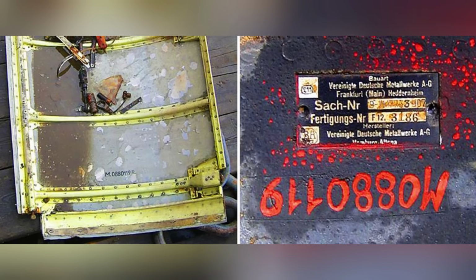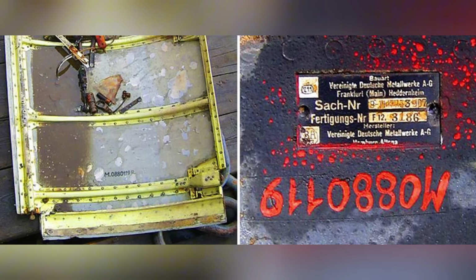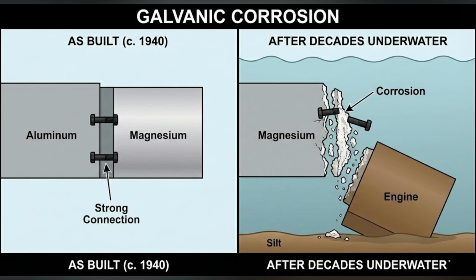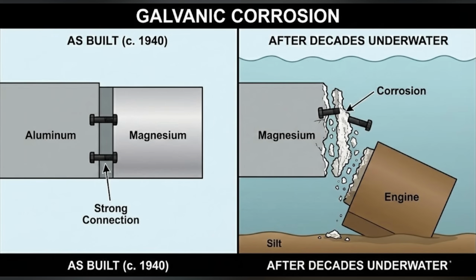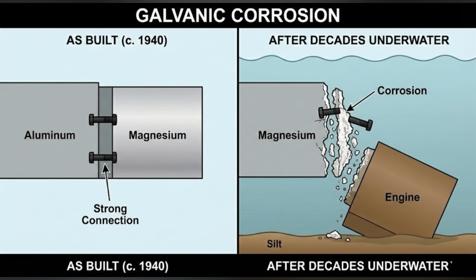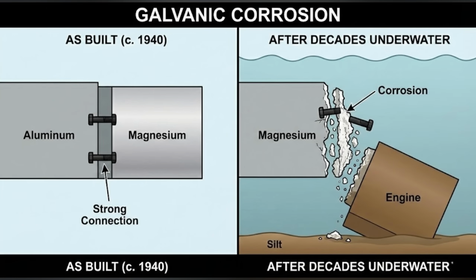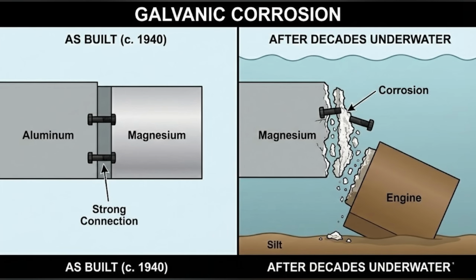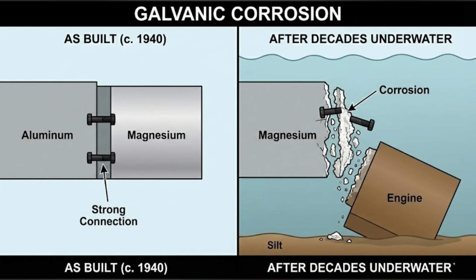This anomaly was not caused by impact damage. It points to selective corrosion in an airframe built from dissimilar metals, often nicknamed magnesium rot, when magnesium-rich castings are involved. To save weight, aircraft of the era could use magnesium alloys in certain heavy fittings, including engine bearer structures and other cast parts. Magnesium sits far less noble than aluminum, so when the metals are coupled and immersed, the magnesium-rich pieces can corrode preferentially. Over decades, those parts may lose their strength and crumble into a chalky residue, leaving heavy assemblies like engines no longer properly supported by their original mounts.